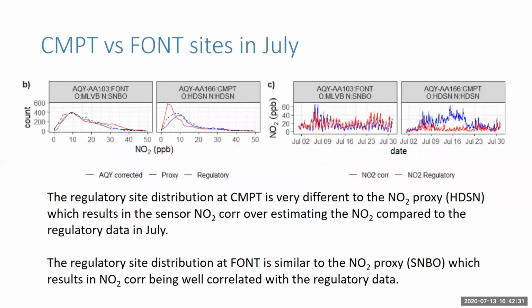I'm showing 2 different graphs here. On the left-hand side are the site distributions at Compton versus Fontana, and on the right-hand side you can see the time series data for the 2 sites. And what's clear is that the regulatory site distribution at Compton is very different to its NO2 proxy at Hudson, which results in the sensor NO2 correction overestimating the NO2 compared to the regulatory data in July. Whereas the regulatory site distribution at Fontana is similar to its proxy at SNBO, which results in the NO2 correction being well correlated with the regulatory data. So this shows the importance of the requirement that the distribution of the proxy is similar to that of the site.